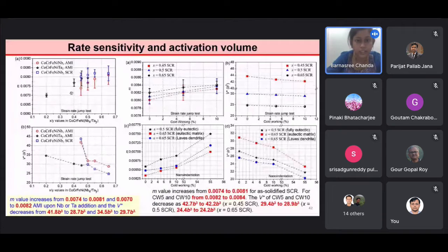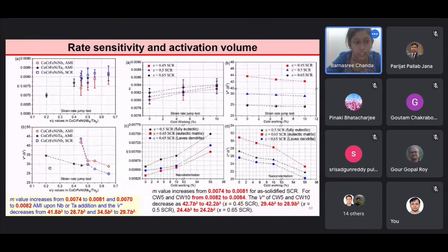The strain rate sensitivity and activation volume. Figure A and B show the strain rate sensitivity and activation volume with the addition of the alloy, that is, with the addition of niobium and tantalum, and we compared the suction casted rod and the arc melted ingot. With the alloy addition, there is an increase in the strain rate sensitivity. Further, the strain rate sensitivity is higher in case of suction casted rod than that of the arc melted